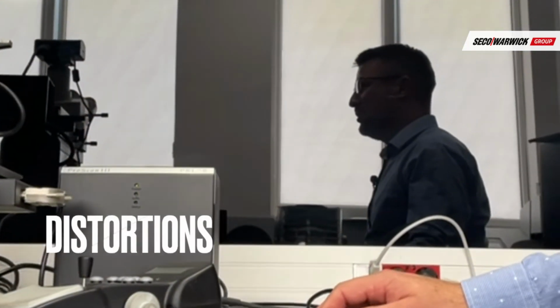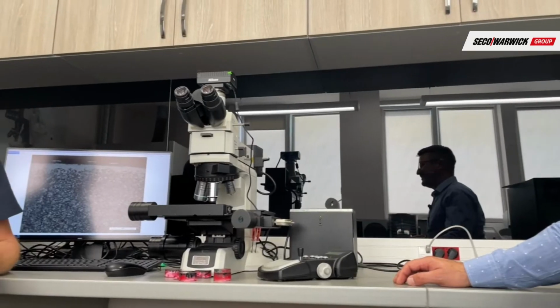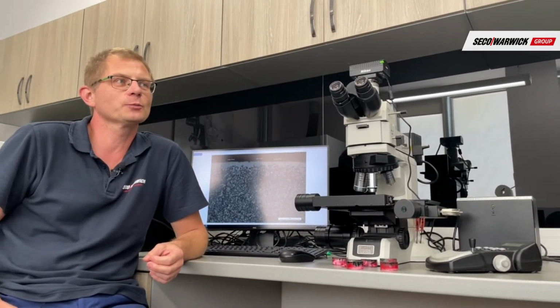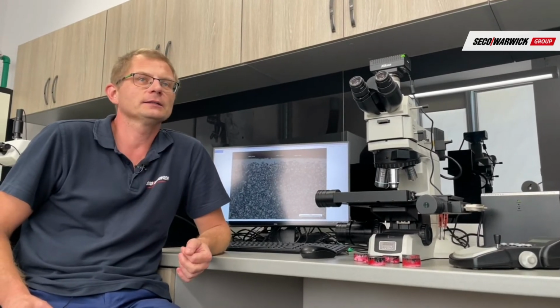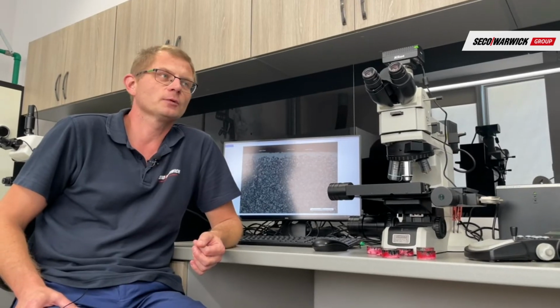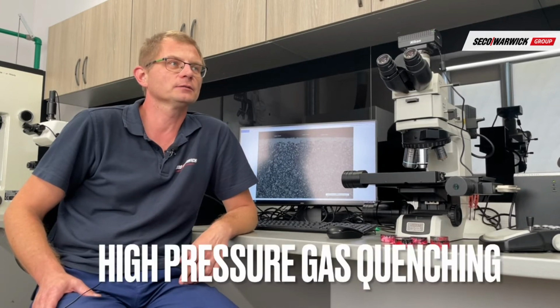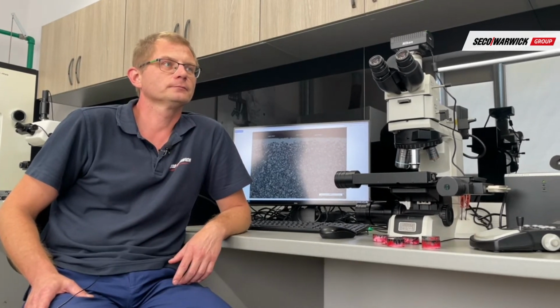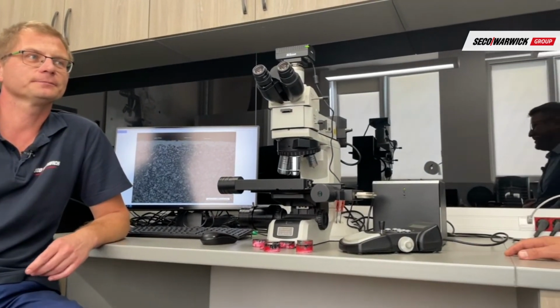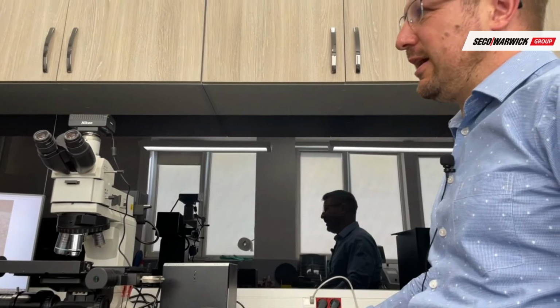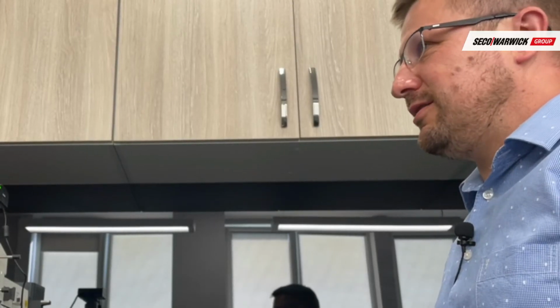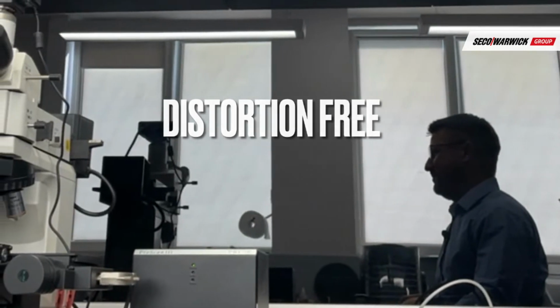Michał, let's talk a little bit about distortions. Wow, distortions. Distortion is a hard subject for low pressure carburizing or even hardening itself. Distortion always occurs after carburizing, low pressure carburizing. We can only minimize these effects using different quenching media. The best is high pressure gas quenching. Nevertheless, we cannot avoid it. I would say that this is a point in favor of nitriding, because nitriding is practically free of distortion.